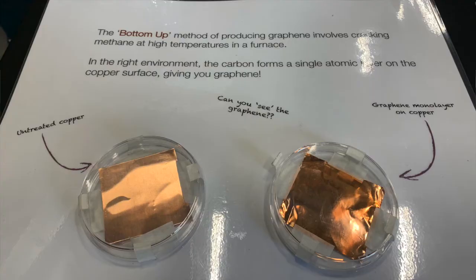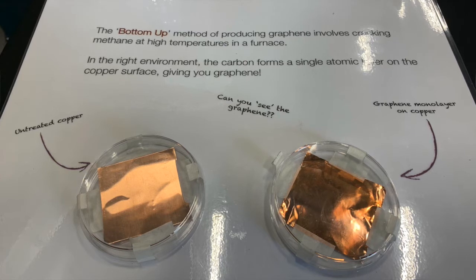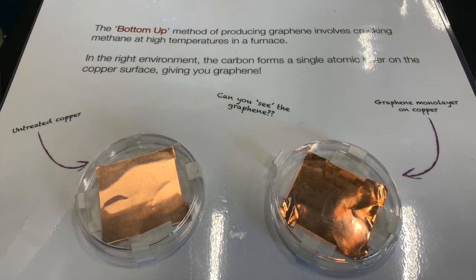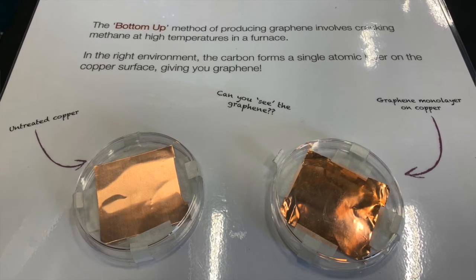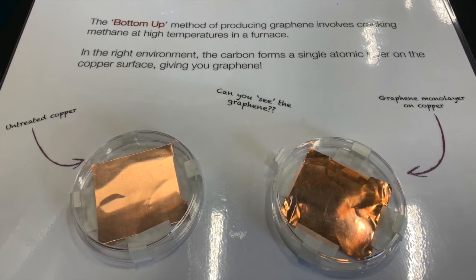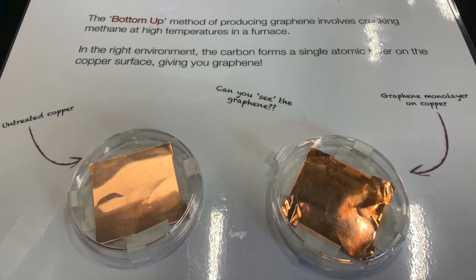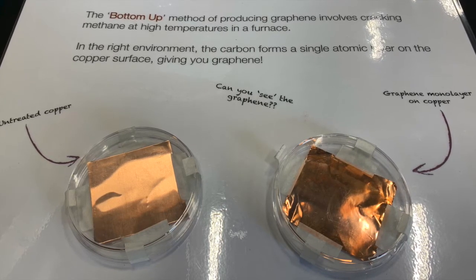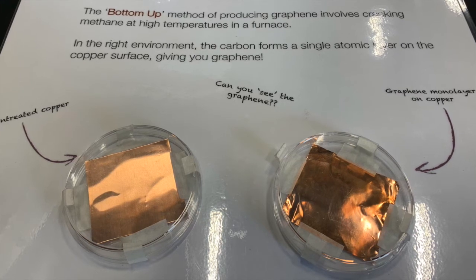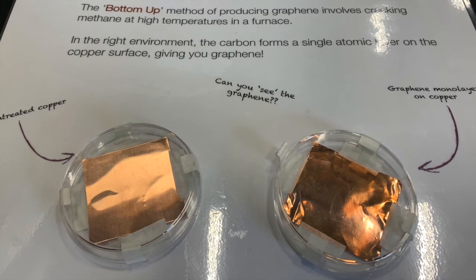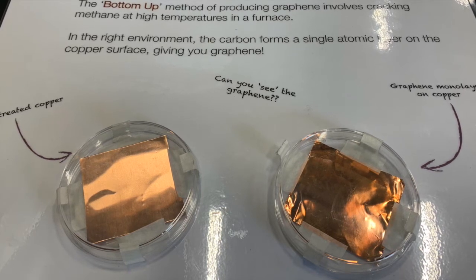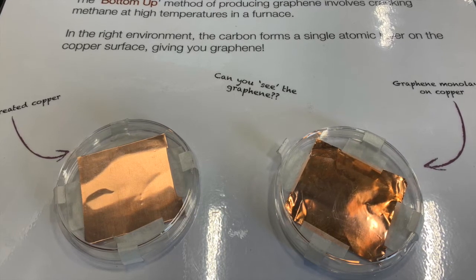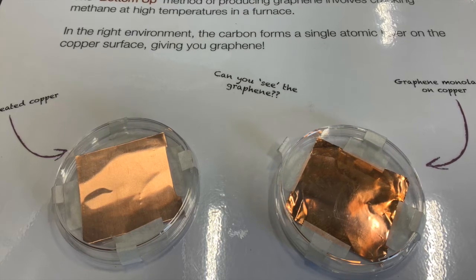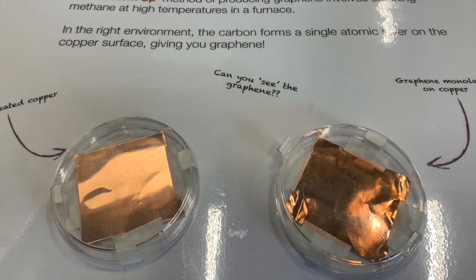So the way that we make this material, to answer your question, is a process called CVD. It stands for chemical vapor deposition. This is a very well-known process. It's been around for decades. The computer chip guys have been using it for a long time. It's used in many other industries as well. And chemical vapor deposition is actually very simple. We take a chamber, and we have several of them here at our factory. And in this chamber, in this case, to grow what we want to grow, we use copper foil, as you saw Adrian hold up there, as the growth substrate.